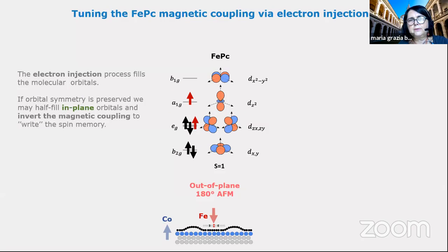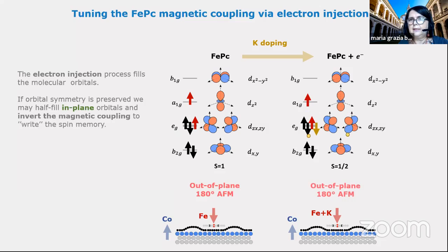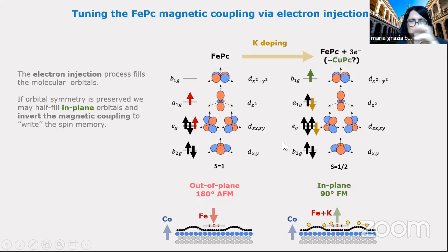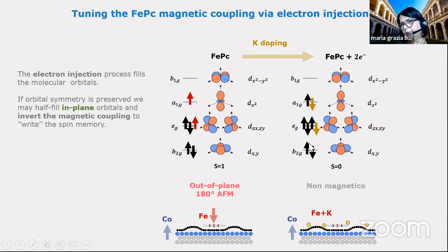In this case, if you remember, this is the configuration, the iron phthalocyanine. And in this configuration, we know the coupling is antiferromagnetic. Then we put potassium on. And if you put potassium, you just start to fill your orbitals, the first one, the second one, and so on. This is a rough representation of the system, but okay. In this configuration, the system is non-magnetic.